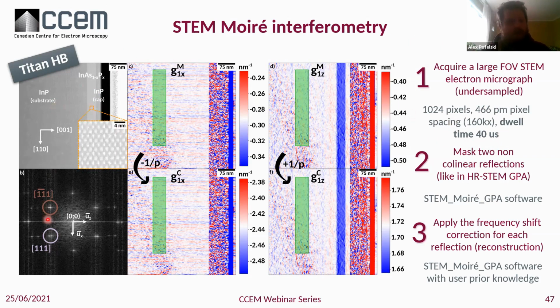Then after, you just mask 2 non-collinear reflections like we did in GPA before, and this is done in the STEM Moiré GPA software, and then here we need to apply this correction. So this is what is showing. You have, for example, this is not the phase directly, this is the G. So the phase is converted into a G. And then those G, M for Moire, C for crystal, need to be corrected by this small correction. And this requires an input from the user. I won't go into the detail here, but the complexity is to find those values to be able to do this correction.